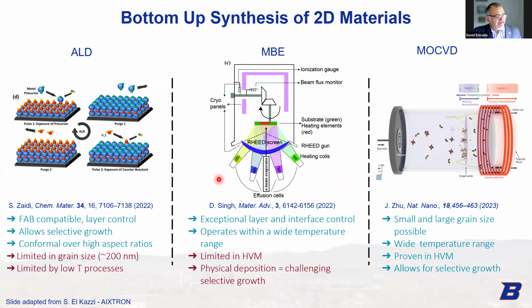We have atomic layer deposition, which is driven by kind of the surface chemistry and the chemical reactions to grow your layer. Very fine precision, can be slow at times, but very good selectivity and very fine control of the layer growth, right? And it is fab compatible. One of the key things with ALD is conformal, right, over high aspect ratios, where ALD coming out. But if you're looking at 2D materials, most of these are low crystallinity, right?